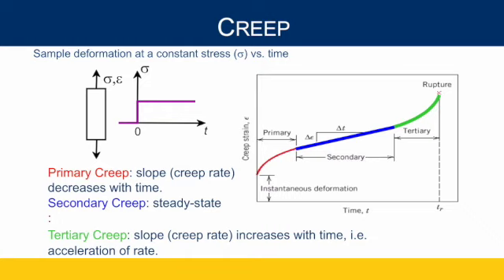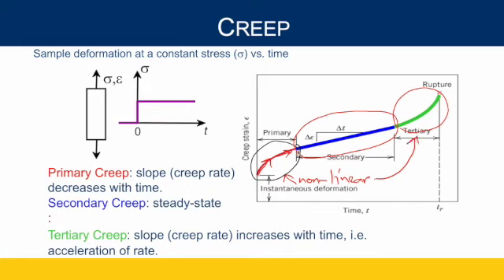So we model this as 3 ranges of creep. We have the primary, which is the start of the strain. The strain starts off kind of quickly and then it starts to slow down. You can see the slope here, with respect to time. This is kind of a nonlinear section, typically not modeled because of the nonlinear aspects of it. And then at the end, we see a similar thing. The rate of creep increases again until it fractures over a smaller amount of time. This also is a nonlinear effect.